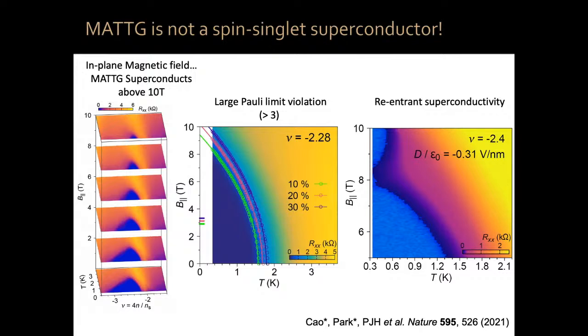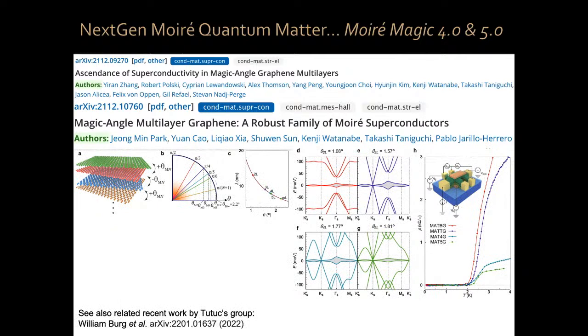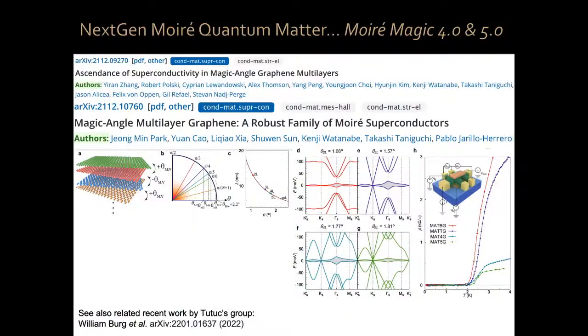Now, I told you that we are busy with Moire Magic 3.0, but actually we continue. So now we have Moire Magic 4.0 and 5.0. As of a few months, a couple of groups and ourselves. As you can see in this field, the competition is huge. You post a paper, and then immediately 3 papers appear in the archive the same day or so. What we have discovered recently is that the magic angle multi-layer graphene is a family of robust Moire superconductors.